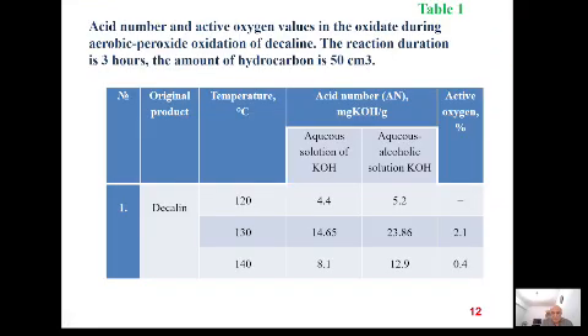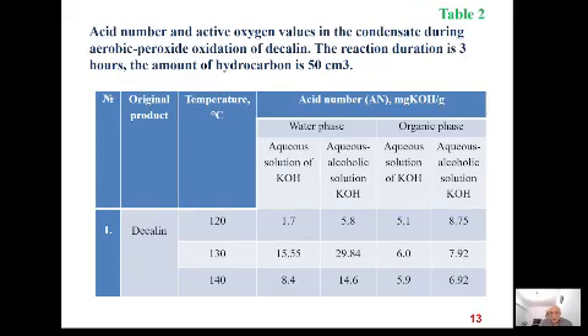Slides 12 and 13 demonstrate, respectively, the acid number and active oxygen index values measured in the oxidate and condensate during aerobic peroxide oxidation of decalin alone. The reaction duration is 3 hours. The amount of hydrocarbon is 50 milliliters.